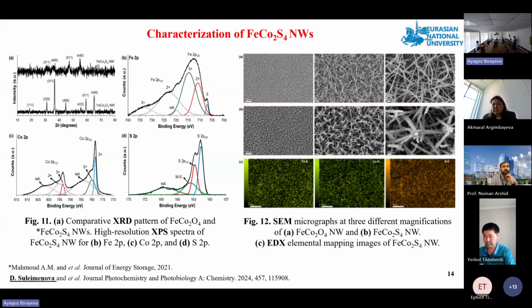Okay. And about SEM, maybe I missed this information. Did you calculate any parameters of the nanowires that you prepared from SEM pictures, for example the size of these nanowires, the width? Yeah, we checked SEM analysis, and this is the diameter for oxide and sulfide. For oxide it gives around 92 nanometers, for sulfide approximately 199 nanometers, because we changed oxide ions to sulfur.